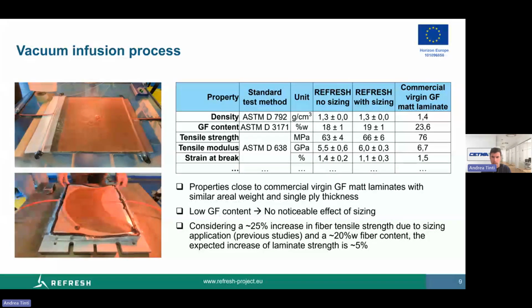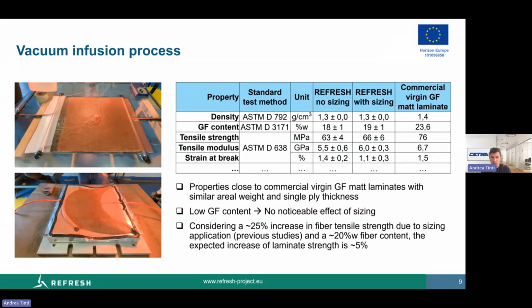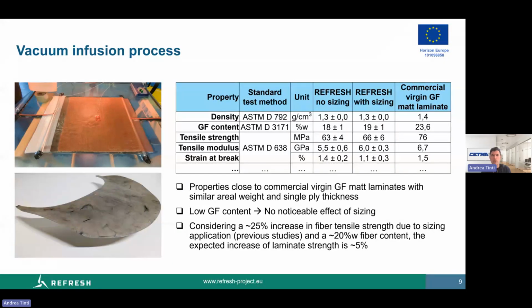As a matter of fact, in this case, no significant effect of the sizing was noticeable, but it was probably due to the low glass fiber content in the laminate, that you can see was below 20%. So the expected increase of laminate strength is in the range of the properties' standard deviation.